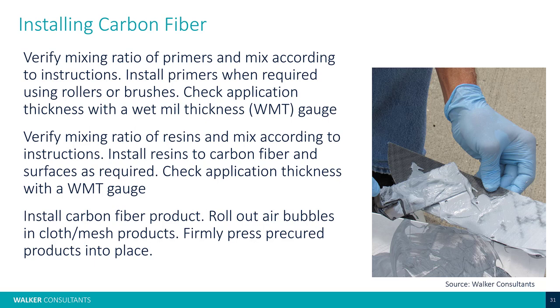Yep. And then the resins, as we're putting resins on. So you've got your primer on, that's all set and ready to go. You want to make sure if you need the primer to be tacky, or if you need the primer to be fully cured, whatever the manufacturer's requirements are on that. Then you want to put on your first layer of resins. Check with the manufacturer again. Mix those, that's a part A, part B type thing too. Make sure you're doing everything per proper ratio, otherwise you might not get proper cure on the product. And then again, check the application thickness with the wet mil thickness gauge.